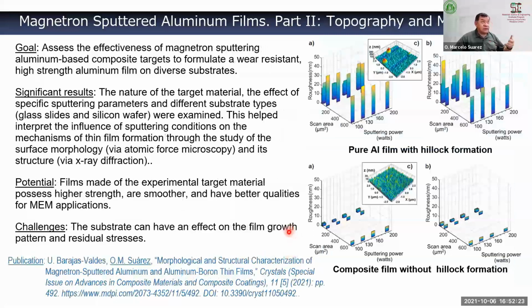I said that we were demanding high reflectivity, and that high reflectivity is related to the surface of the material, particularly the roughness. So we did this work using our AFMs that at that time were working. And we found out that a problem with soft aluminum deposited on whatever substrate you want, either glass slides or silicon wafer, is that it had a high roughness. One of the reasons is the residual stresses induced by the deposition. As a result, you ended up with hillock formation on the pure aluminum film.